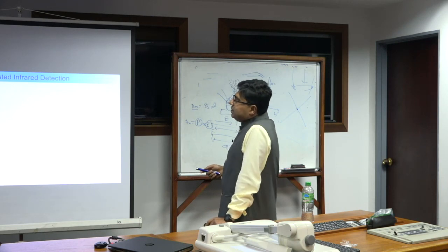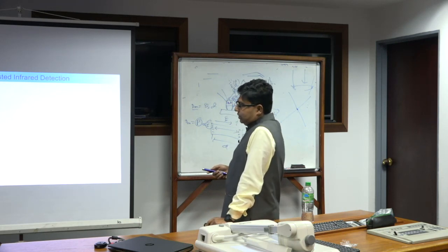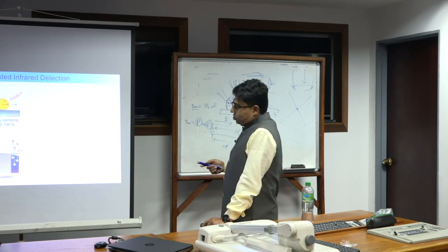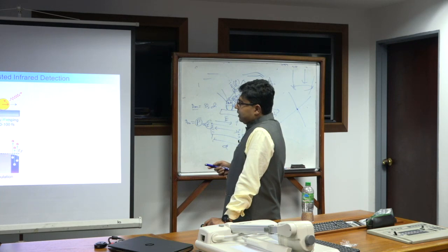So now you excite the plasmon on the graphene, because it has a lot of free electrons, because it is a semi-metal. Now, at the tens to hundreds of femtosecond time scale, you get Landau damping, which means you re-radiate some of the photons back because you excite carriers. Some of the carriers will re-radiate, because as soon as a carrier or electron moves, it re-radiates photons back.